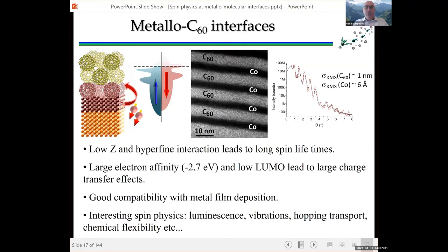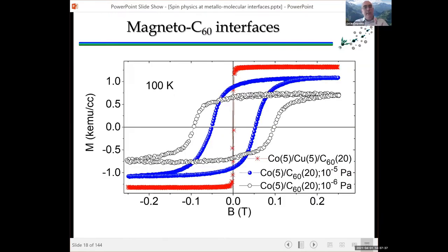So our first studies were with cobalt and C60, and the first thing that we noticed is that if you compare, at 100 Kelvin or less, the hysteresis loop of cobalt with respect to the hysteresis loop of cobalt with C60. In here we measure cobalt and then we put a spacer of copper and then the C60, you can see the coercivity of your film is very small, as you would expect from a typical transition metal, thick enough, 5 nanometers, measuring in plane. But as soon as you put C60, you enhance that coercivity and you reduce the magnetization of your sample. Not only that, but the better the vacuum you do this at, the bigger the effect.